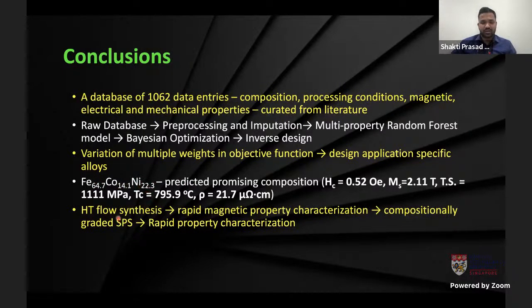To remove the heterogeneity in the data, a high throughput experimental methodology was used, which is basically high throughput flow synthesis, followed by compositionally graded SPS in order to make bulk samples, and further the properties were characterized rapidly.